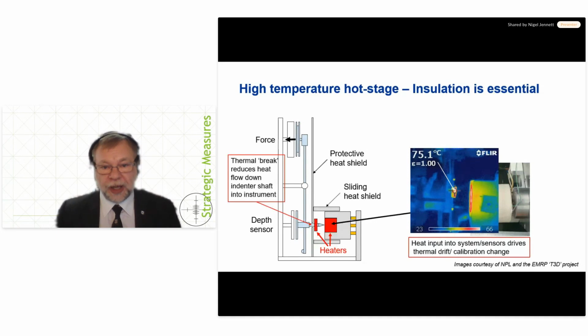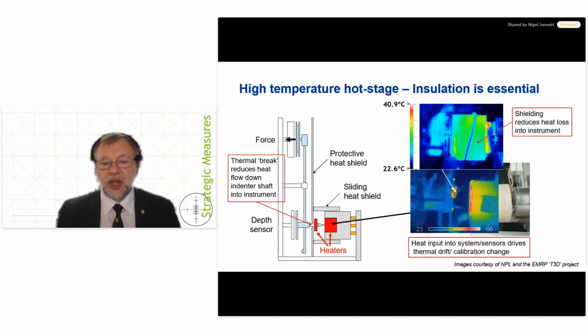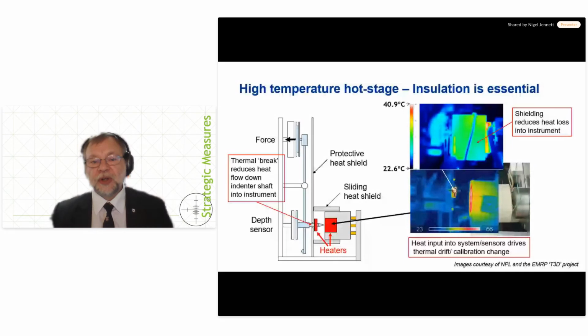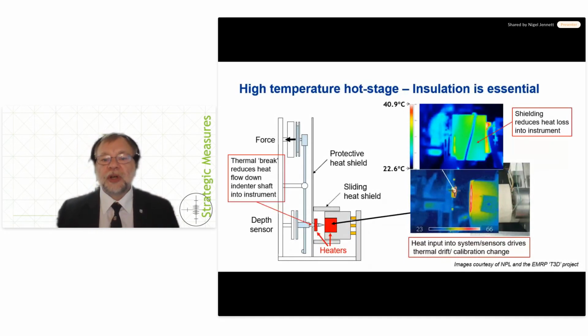So you want to stop heat getting into your system. So wherever there is a path out of the hot zone into the instrument, you need to stick an insulator. So thermal breaks in the indenter shaft are a good idea, and sticking a shield on the outside of the hot zone reduces the temperature of what the inside of the machine sees. So you probably can't quite see the temperature here, but this bit here is around about 40 something. If out here, and this bit here was about 75 degrees, you cover it with an insulator and you can see the mid-range of that is around about 30 degrees C.